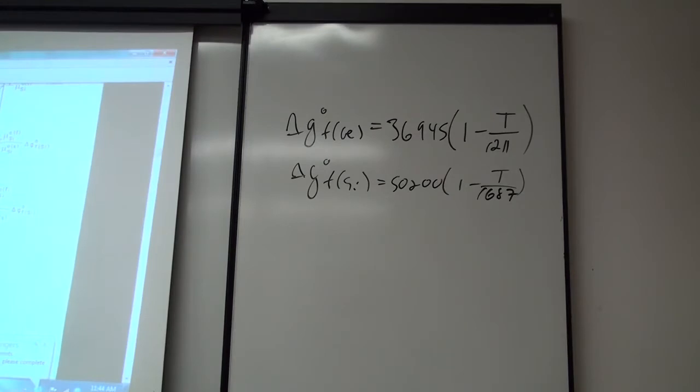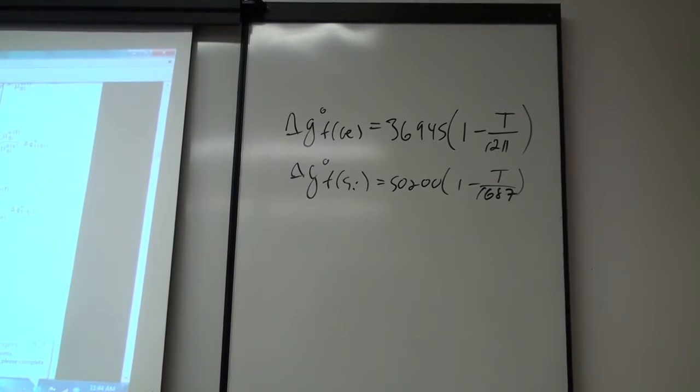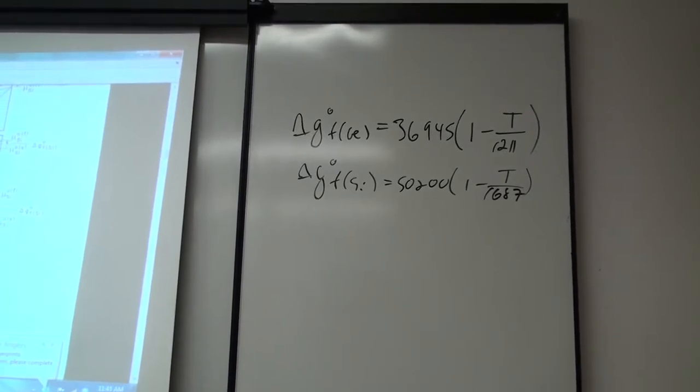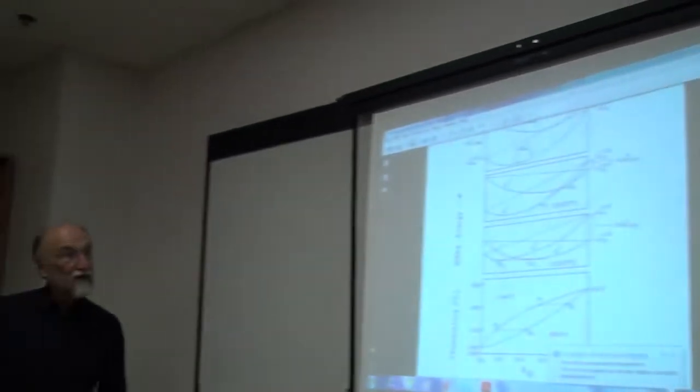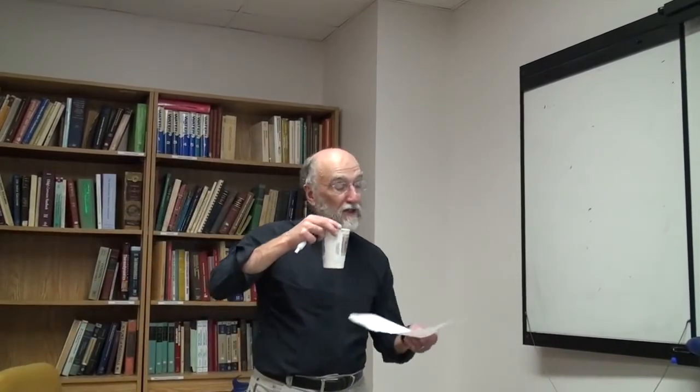Okay, so now I can go back into these. Those are my two equations which I need. I needed the Gibbs energy of fusion. I've made the assumption that the CP liquid equals CP solid. This is not necessary, of course. The heat of fusion is the heat of fusion at the melting point plus the integral of CP dT, and you can get CP, you can get the whole thing. You don't have to assume the heat of fusion and temperature of fusion are independent of temperature. You don't have to assume CP solid equals CP liquid to do the calculations. That's good.